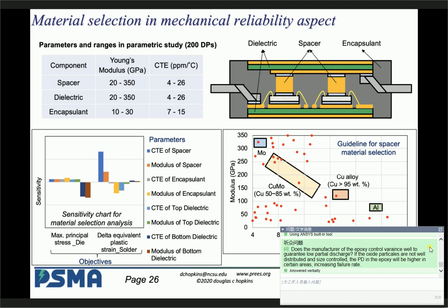It's nice to be able to work with companies that have extensive capabilities. But what they don't have is the applications understanding. We look at our structures, because they're doing their testing to a standard, and then we put that into our modeling. But that doesn't mean that when you develop a structure, which goes back to the question about electric fields and intensities, you're not exceeding what your materials can handle at the highest point of field intensity. So we look at materials that we have a lot of confidence in to start with, working with manufacturers that have good reputations. But on the other side of the coin, we do our own testing to make sure that within the structures we're looking at from an applications point of view, we're still able to use their numbers as design guides in what we do.